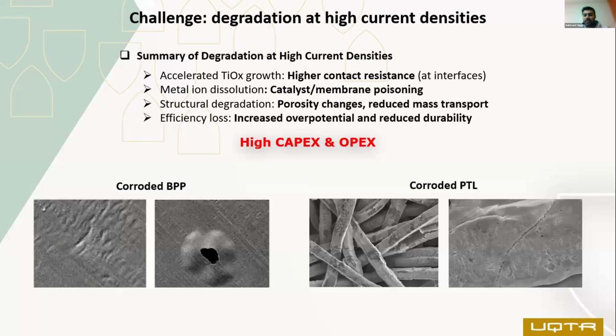Apart from resistance increase, corrosion of titanium can also trigger metal ion dissolution, also called catalyst membrane poisoning. Structural degradation of titanium PTL results in porosity changes that will further reduce the mass transportation, including efficiency losses like, as we discussed, increased overpotential and reduced overall durability of the PEM water electrolyzer cell.